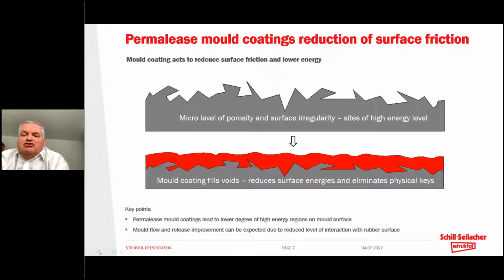So in terms of the effect that we want to achieve with the mold coating, if we look at, if you like, almost a map, or a model, a depiction of the micro surface of a mold, we can see even a very polished and flat mold will have micro levels of porosity and surface irregularity. There are sites of high energy level, both in terms of physical keying, so interlocking of the mold and the mold deposits into the undercuts that are present on the mold, and active sites, if you like, from the metal ions that are present on the surface of the mold that allow chemical interactions to occur with those mold deposits. The target with any mold coating is to fill in, if you like, these voids to produce a more regular surface, a lower surface energy, a flatter and smoother surface as depicted by the red infill that we would achieve by a coating. And particularly with the semi-permanent coatings, the idea is to cross-link this red layer to provide a very durable and low energy coating to the surface of the mold.